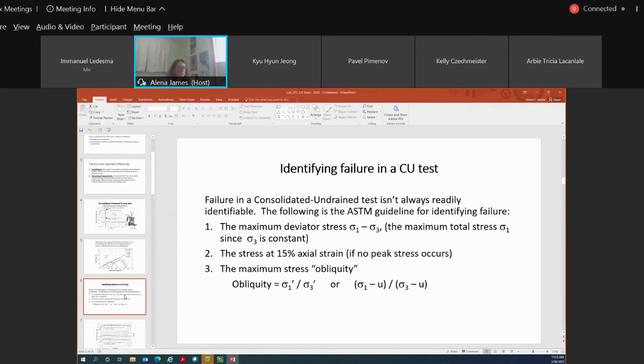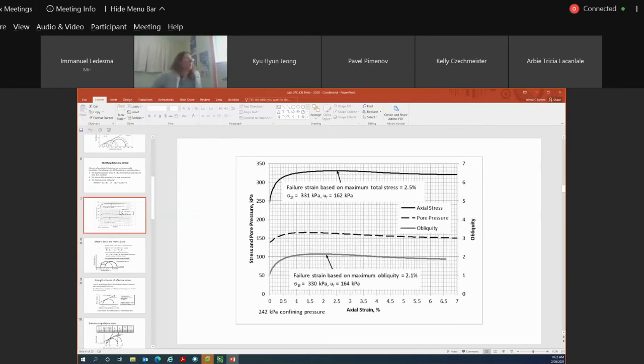Don't spend too much time worrying about this because we're not doing the test in person. Generally, we consider our specimen to have failed when it reaches its peak or its maximum axial stress. Here again is just another plot of axial stress and pore water pressure versus axial strain. So you'll see from this plot here that our axial stress at failure would be this data point. And if we were to draw a vertical line down, this represents our pore water pressure at failure. So this value right here, which is about 164 kPa. This isn't our maximum pore water pressure value, but this is our pore water pressure value that we use when we're determining our effective axial stress and our effective confining stress.